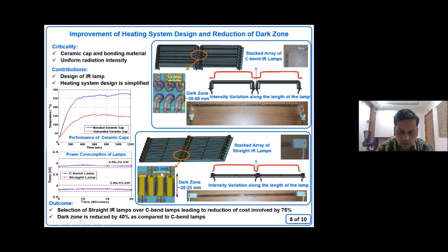So we have maintained a very close distance of 30 mm between these two lamps. In this way, we have reduced the dark zone from 50 to 60 mm to 20 mm. For this, one major challenge is bringing this ceramic cap into the IR region. Now you can see the ceramic cap is at the back side of the IR, so it may not face that much heating. Here this complete thing will get heated up.